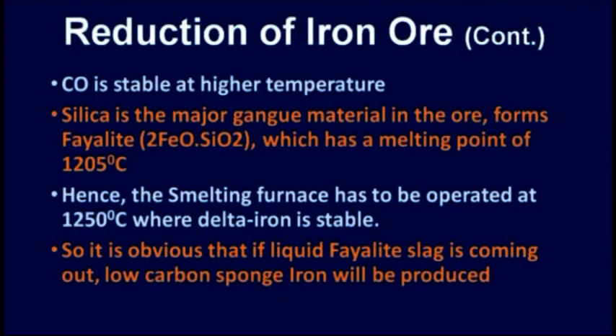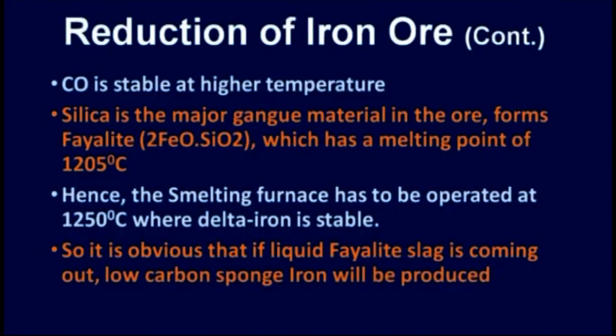As the temperature increases inside the furnace, the silica as gangue present in the iron ore forms fayalite, that is 2FeO.SiO2. It is the slag, and at high temperature it comes out in liquid state. Another advantage of this high temperature is that at 1200-1250 degrees centigrade, delta iron is produced, which is lesser in carbon content. So the ancient iron making process was able to produce iron having less carbon content.